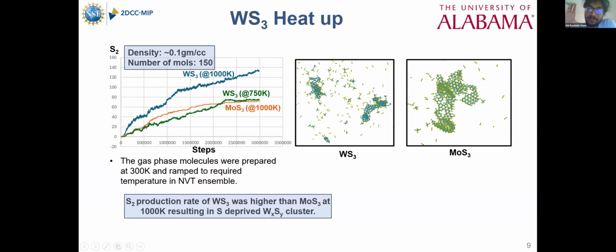This time we had a box with tungsten trisulfide, with a density of almost 0.1 gram per cubic centimeter. Then we increased the temperature to 1000 Kelvin, and we saw that the amount of sulfur created by tungsten species was double the amount of sulfur molecules created by molybdenum species. For the final structures, in the tungsten trisulfide case we got cluster-like structures, but in the molybdenum trisulfide case we saw a good 2H nanosheet-like structure.